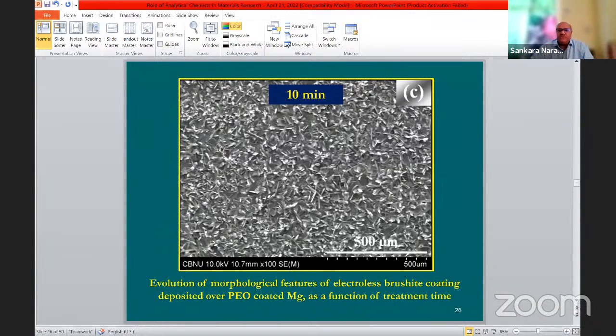During the initial period, we can see the crystals formed here and there. After 5 minutes, you can see the size of the crystals growing. And after 10 minutes, you can see the entire surface is covered by the brushite crystals. So you can see the evolution of the morphology as a function of time. For that, scanning electron microscopy can be effectively used.